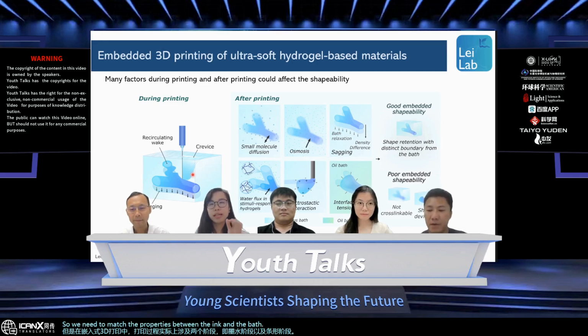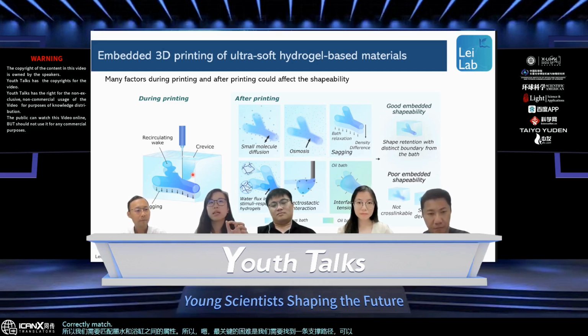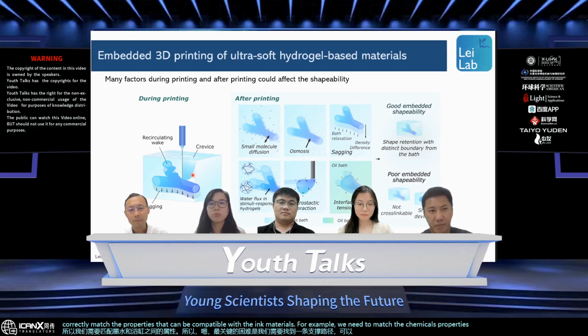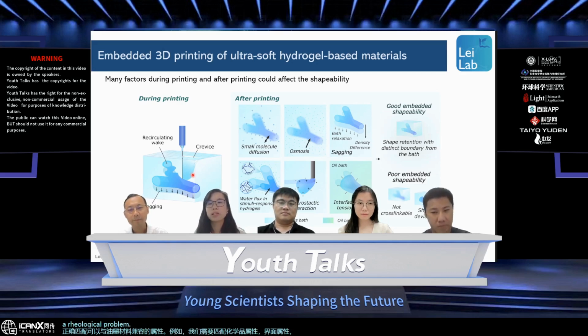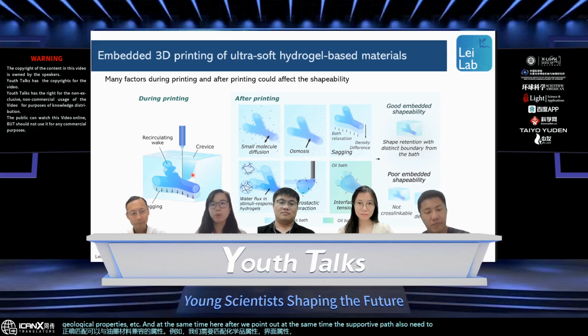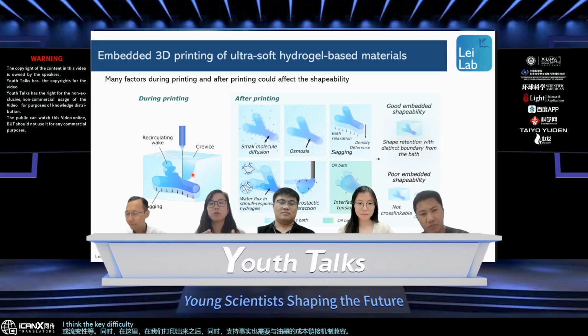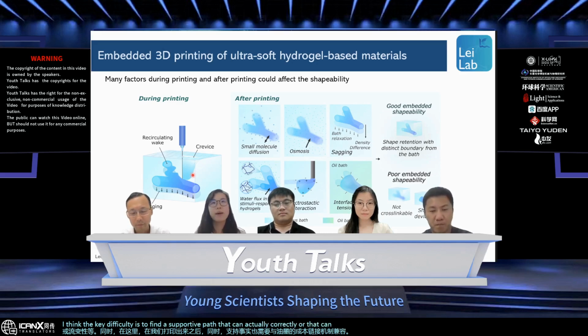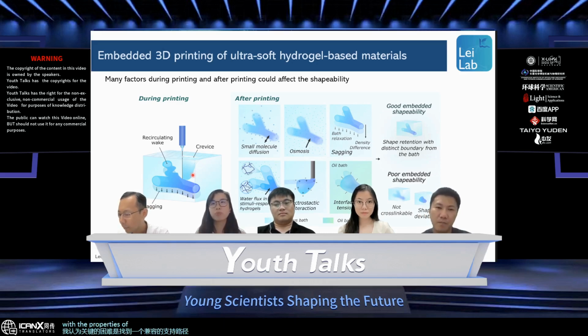So the key difficulty is that we need to find a supportive bath that can be compatible with the ink materials. For example, we need to match the chemical properties, interfacial properties, rheological properties, etc. At the same time, the supportive bath also needs to be compatible with the cross-linking mechanism of the ink. So I think the key difficulty is to find a supportive bath that is compatible with the properties of the ink as well as its cross-linking mechanism.